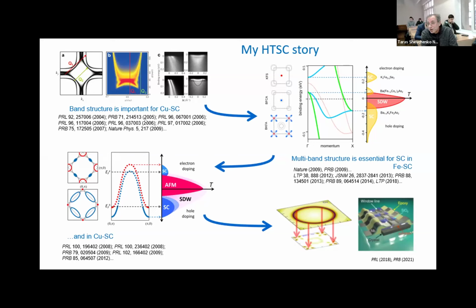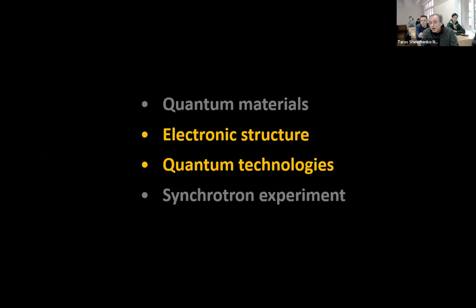I will not focus on it here, but I wanted just to say that, just empirically looking at experiments on electronic band structure in different materials, you can derive some empirical relations and see what is important for superconductivity. It appears that for superconductivity in these compounds, the presence of small Fermi surfaces together with large Fermi surfaces is important. And this is interesting because if we re-examine the case of cuprates, in fact, there is the same situation. Therefore, it seems quite general. But now I want to briefly switch to the case of application: how the geometry of the Fermi surface can be important for applications.